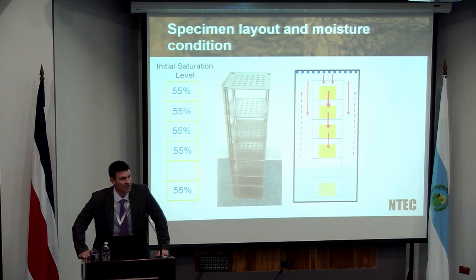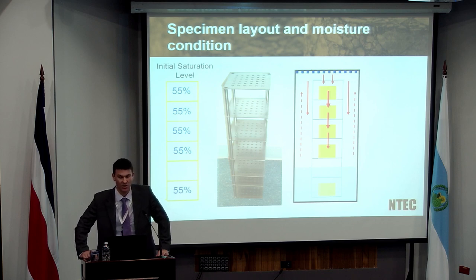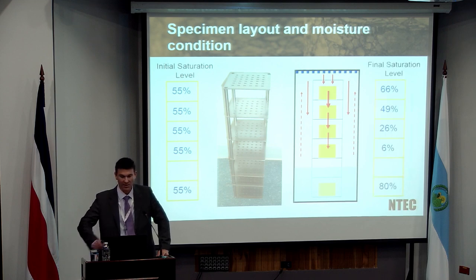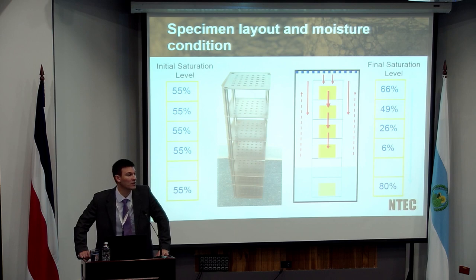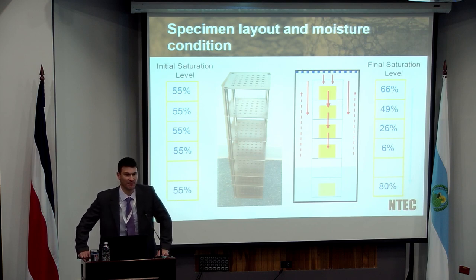The test then artificially forms some kind of environment where water is circulating, and that water is circulating by evaporating from the surface of that reservoir at the bottom and condensing on the top of my pressure vessel and then effectively dripping down. And we know that because if you take those specimens out and measure their water content, in other words, you work out what their saturation levels are, you end up with five different saturation levels. The one under the water obviously is the highest, and that could range. In this particular example, it got up to about 80%. Some of them go up towards 100%. It depends very much on the internal void structure.